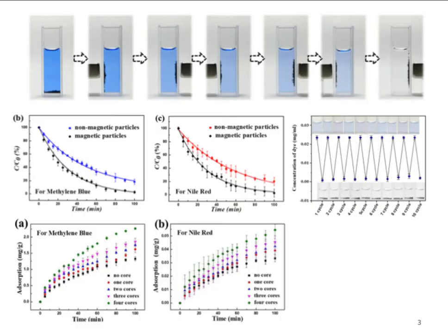And then when used for absorption, the particles were also expected to contact the polar impurities in oil more actively. Thus, to realize controllable movement and recycling, magnetic nanoparticles were also encapsulated in the GO-hydrogel composite particle. And with this improvement, the hydrogel GO particles could be pulled to the side of the container by magnets, as you can see here.